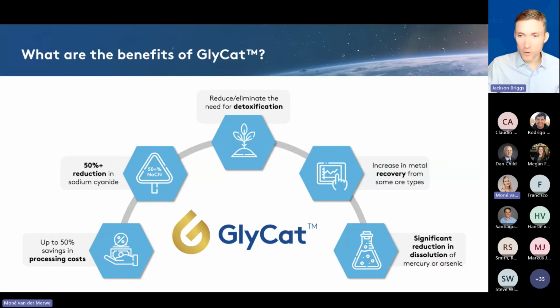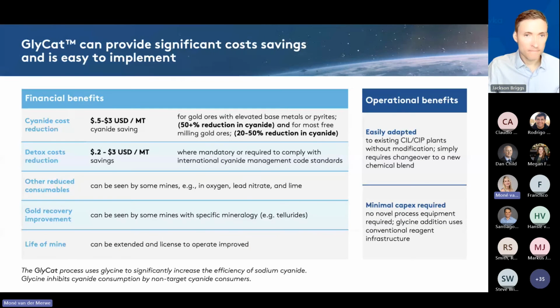So the video earlier mentioned tellurides. That's one where we've seen a significant improvement in recovery and leach kinetics. And then lastly, there's a significant reduction in dissolution of mercury and arsenic with Glycat when we reduce those cyanide concentrations. So the benefits from all these improvements can be quite substantial.